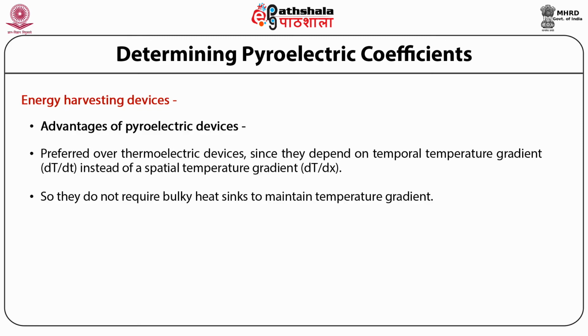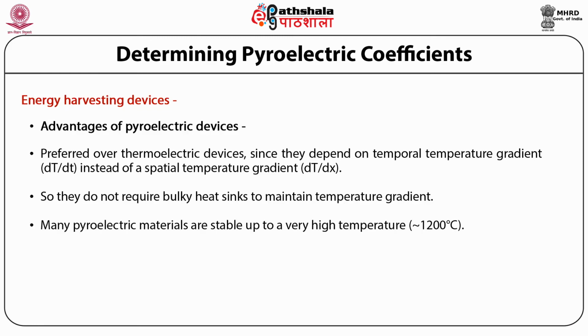Using a limited temperature gradient, a maximum efficiency of 1.7% of Carnot efficiency can be expected using a thermoelectric module, whereas a pyroelectric device may reach the efficiency up to 50% of Carnot efficiency. Many pyroelectric materials are stable up to a very high temperature, and thus they provide a very good advantage over thermoelectrics for energy harvesting from high temperature sources.